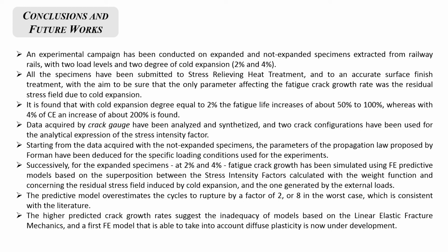Then, for the expanded specimen, fatigue crack growth has been simulated using a finite element predictive model based on the superposition between the stress intensity factors calculated with the weight function and concerning the residual stress field induced by cold expansion and the one generated by the external loads. It is found that the predictive model overestimated the cycles to rupture by a factor of 2, or 8 in the worst case, which is consistent with the literature. However, this suggests the inadequacy of models based on linear elastic fracture mechanics, and indeed a first finite element model that is able to take into account diffuse plasticity is now under development.